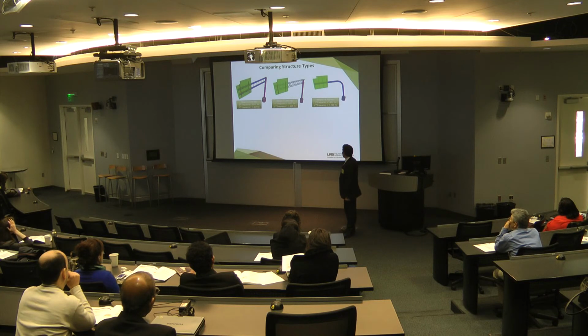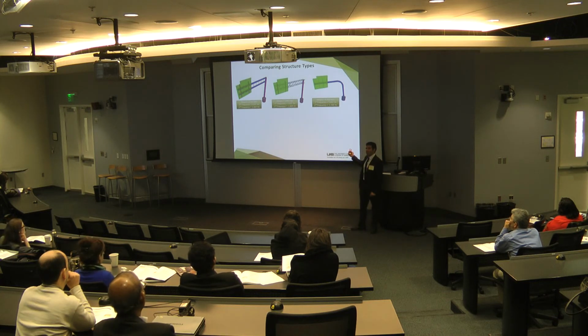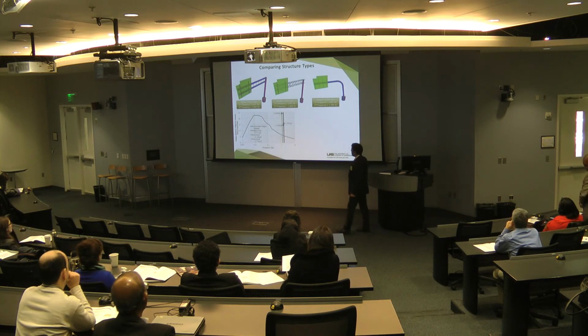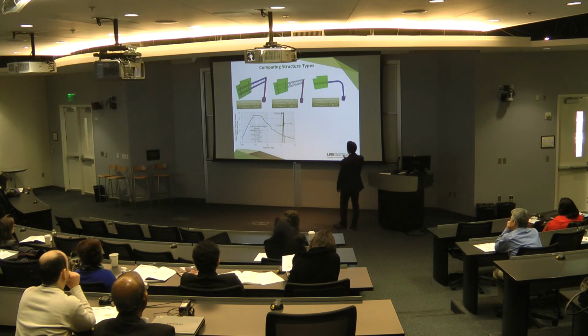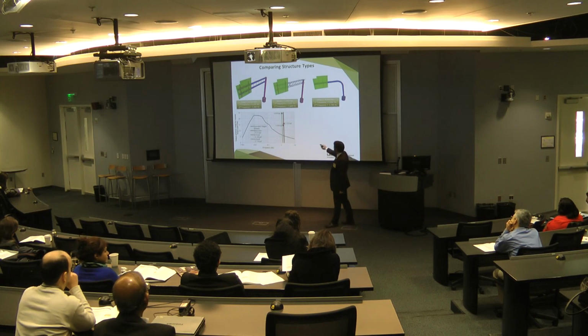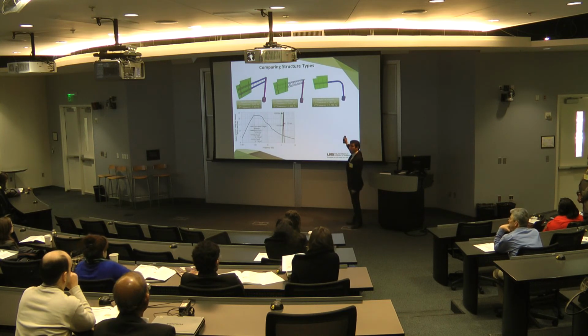And as for frequency, this one has the highest frequency, and then frequency decreases in this direction. So one might say that this is the best. But when I calculated fatigue stresses, I found something interesting. This is due to natural wind gust. I found out that for monotube and 4-chord, stresses were almost the same. However, it was larger for monotube. Why is that? Because I have higher stiffness. The exposed area to wind due to the stocky cross-section of the monotube caused higher stresses. But they were almost the same.